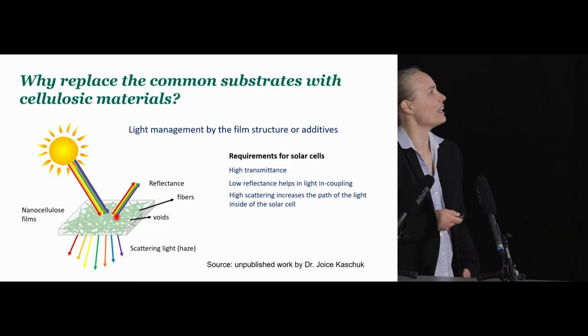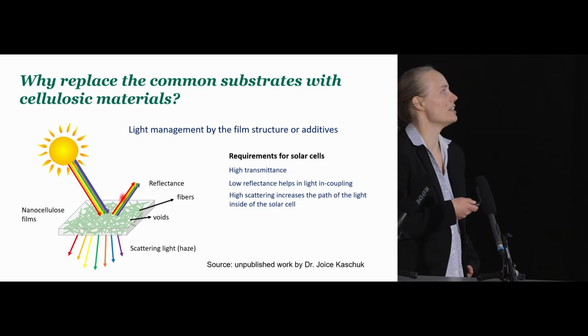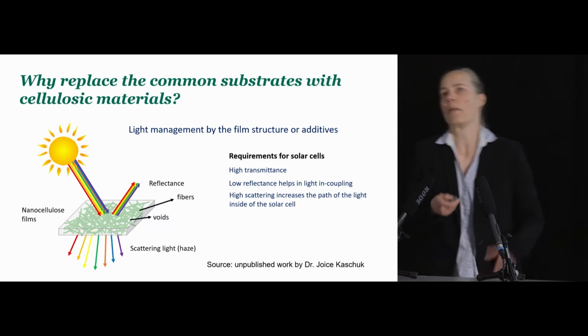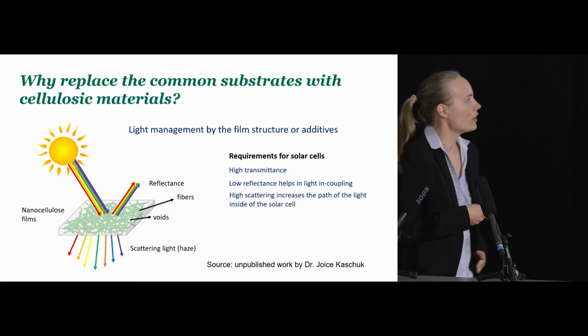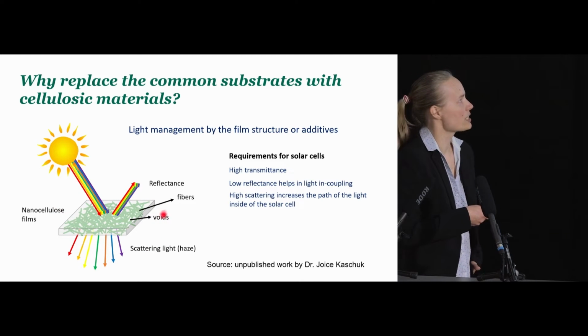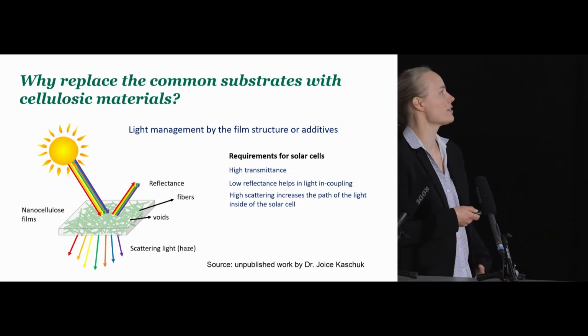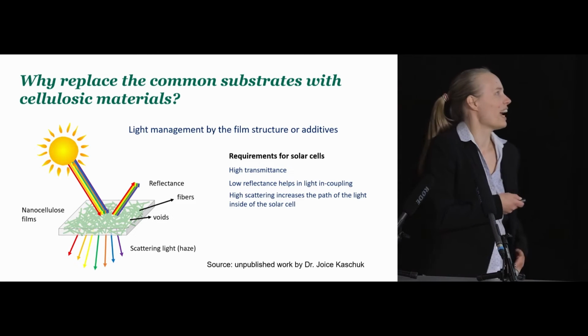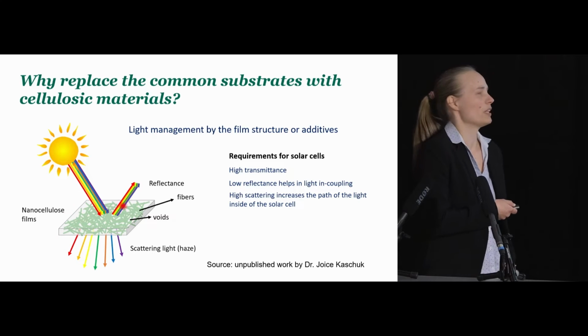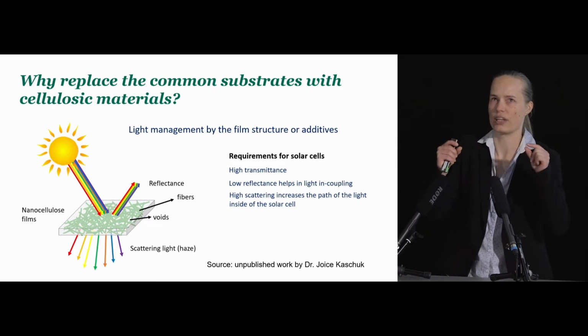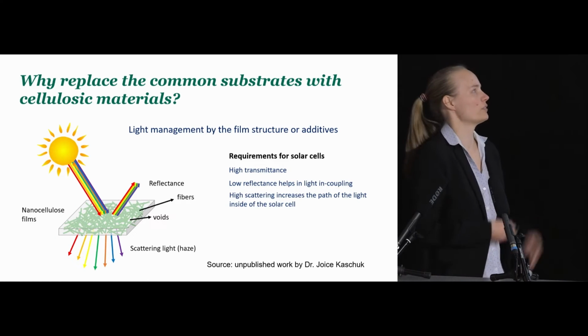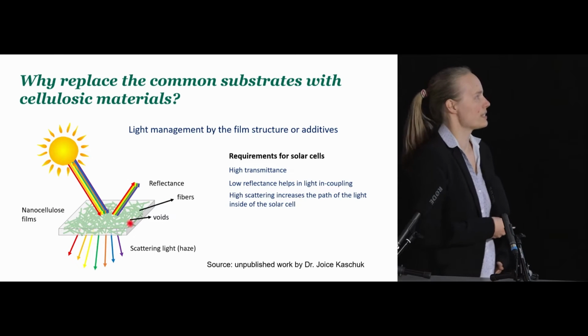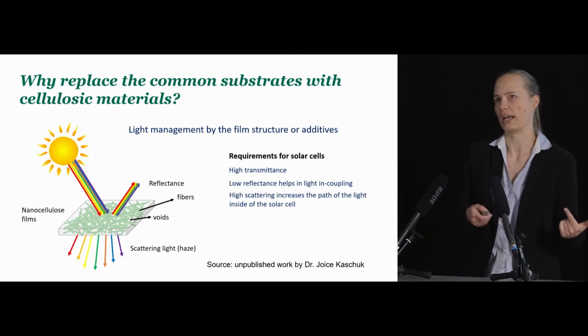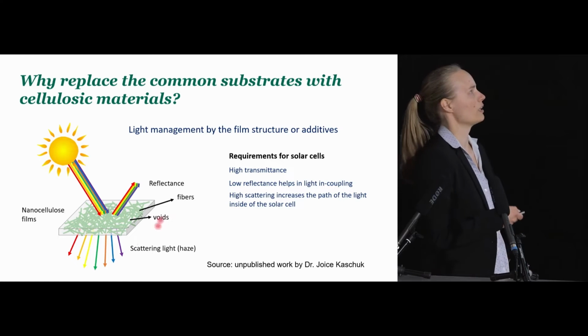And then finally, high haze or high diffusive transmittance, because if we have a thin film device placed just below these light management layers, and we can diffusively transmit the light, then we can actually decrease the thickness of this photonic device below the film, since the optical path length of the light will be increased thanks to the film.